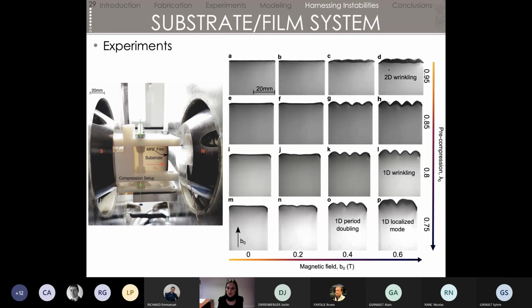And you can see from the top, when you apply very little compression, you can see it on the left images, you do not see much compression initially on the sample. You have trouble triggering that instability with the magnetic field that's increasing when you go to the right. Now, after a certain level of pre-compression, so 0.85, 0.8, you can clearly see that pre-compression on the left images. And as you switch on the magnetic field, you see that wrinkling cleanly appearing as you increase the magnetic field.